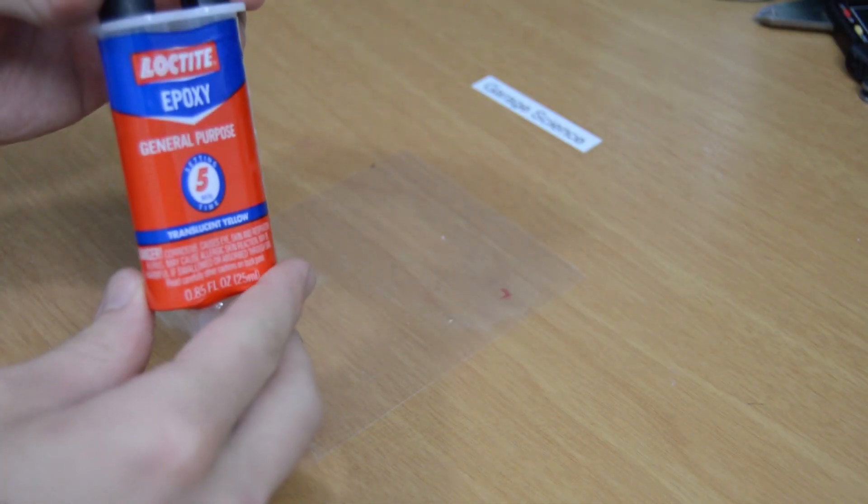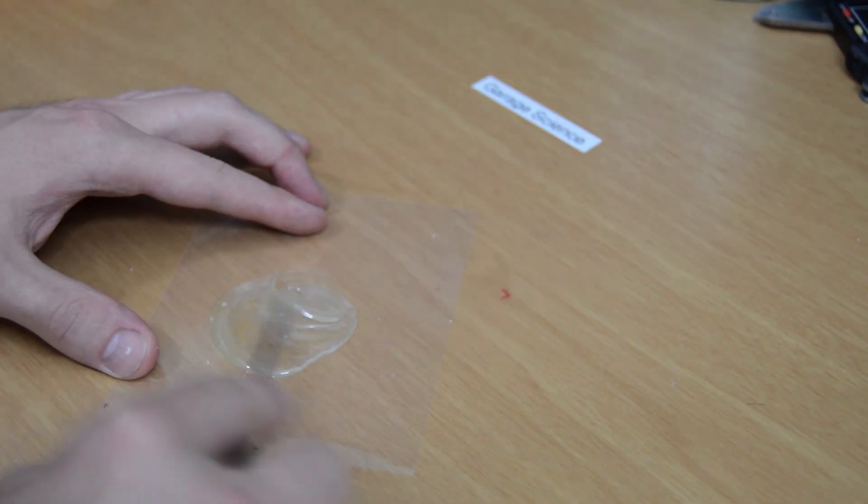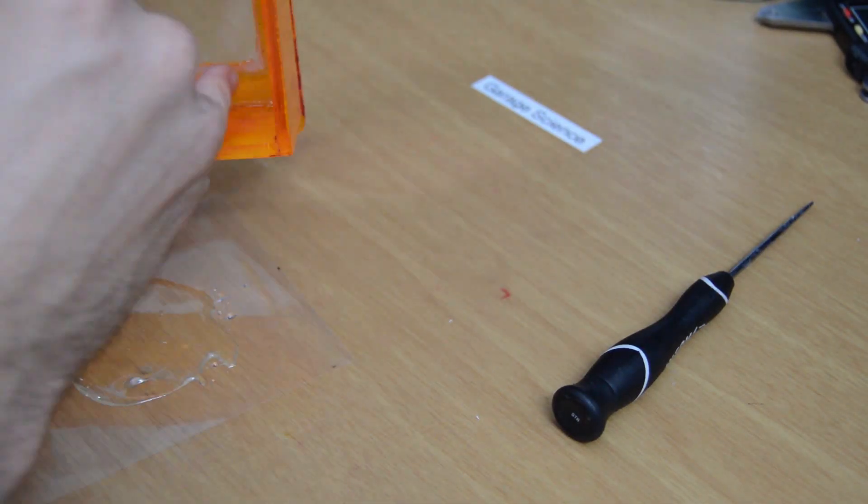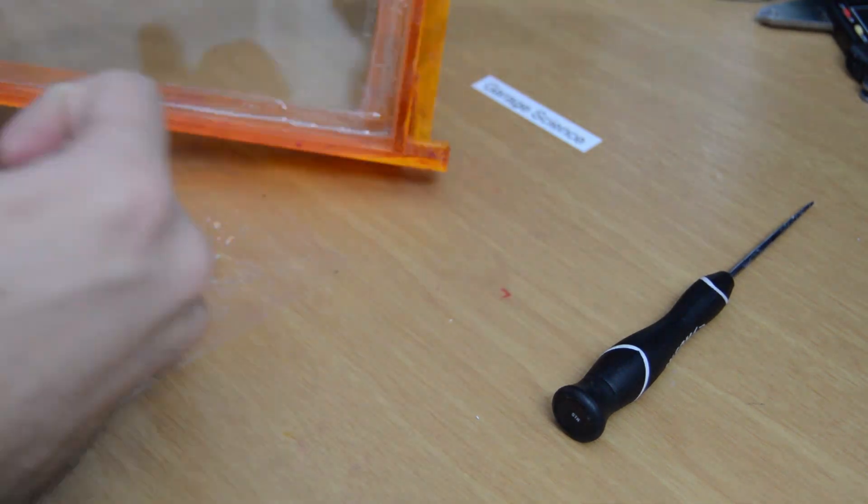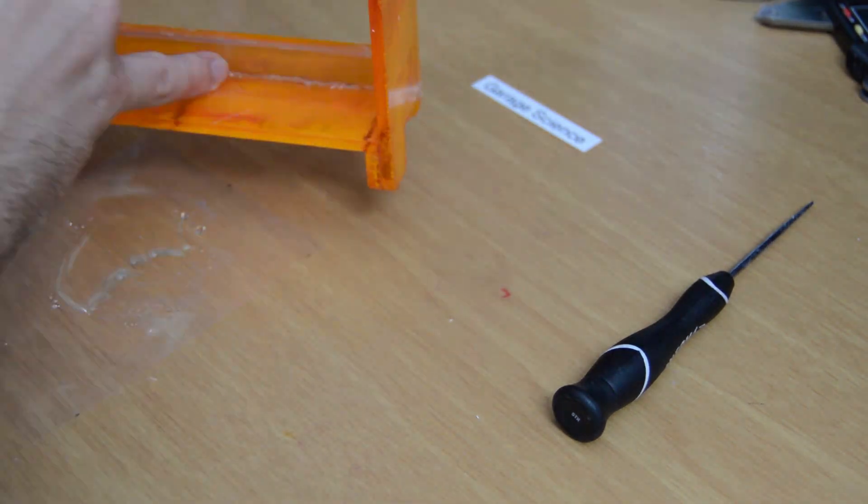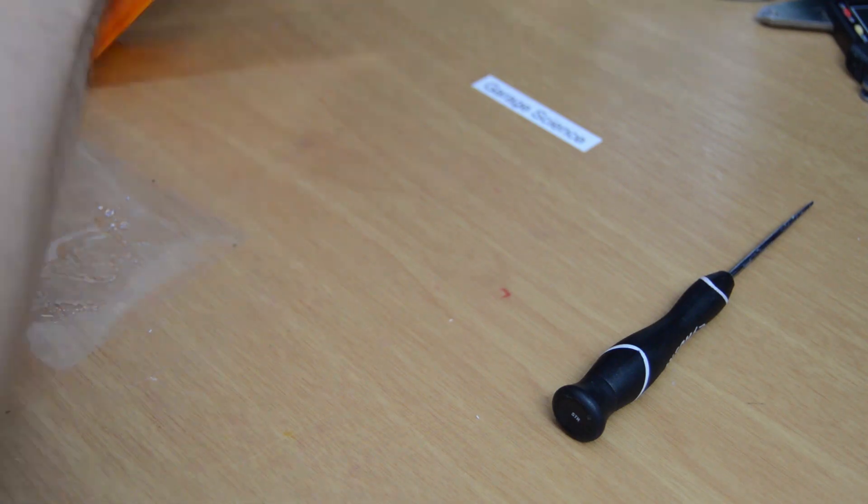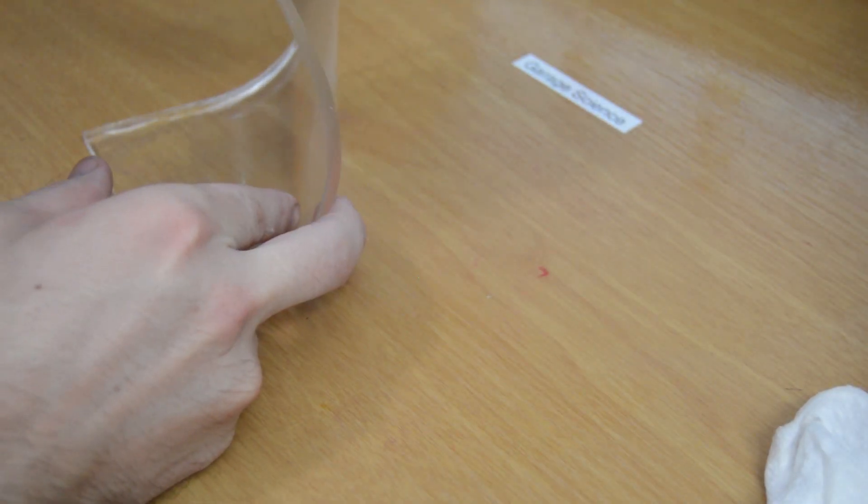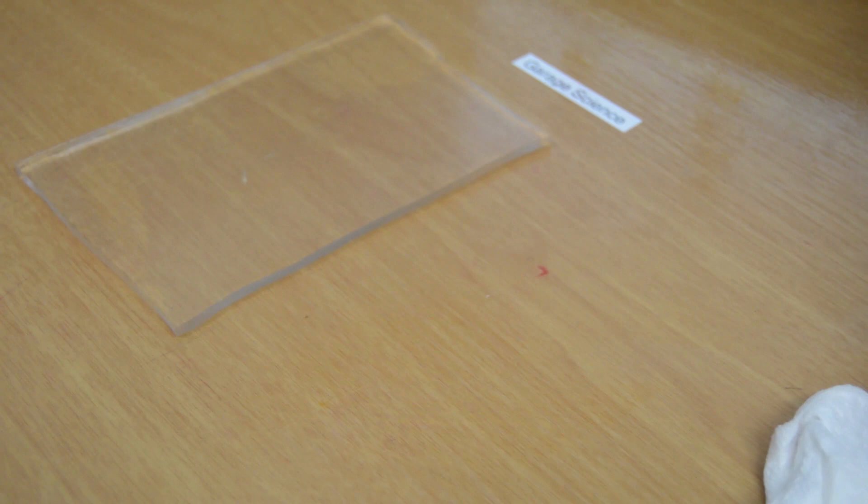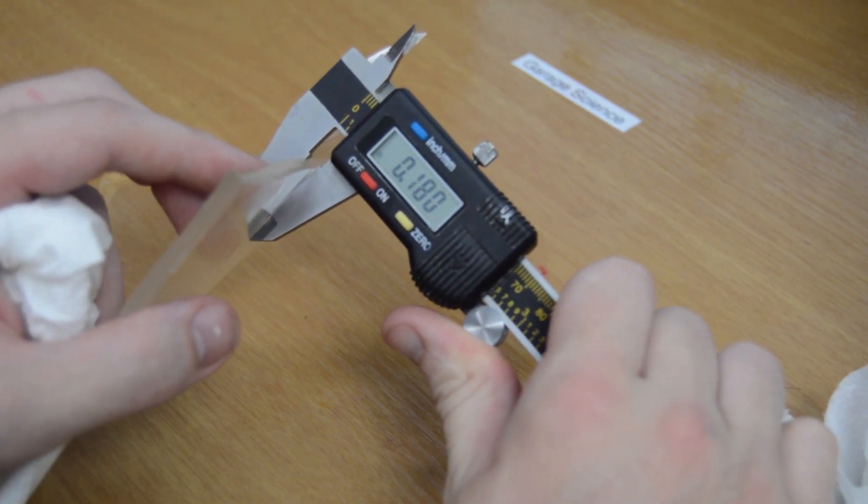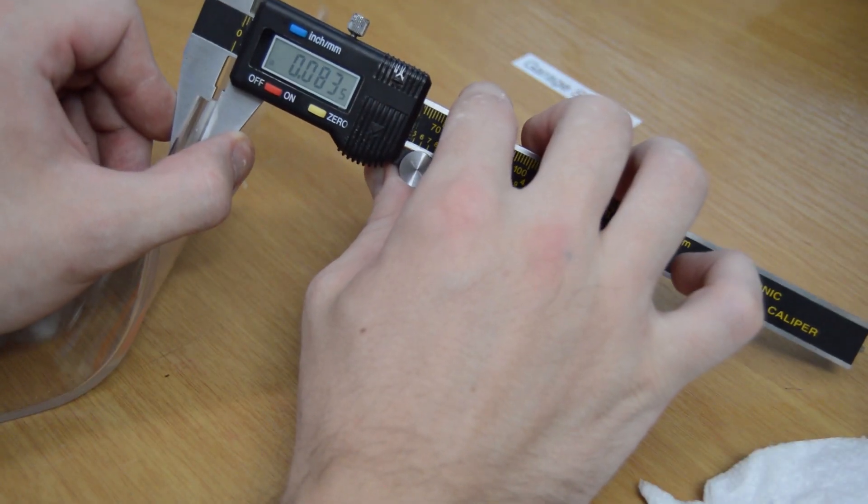Because the glass was put in place with silicone and I wasn't able to pop the glass back out without breaking it, I decided to clean up the excess silicone around the edges and use an epoxy in the corners and around the edges where the silicone was to provide a barrier. An additional thing I discovered was that the 11 tablespoons of PDMS and curing agent I initially used created a significantly thicker coating than I was imagining it would, and it ended up being about twice as thick as the original coating of PDMS.